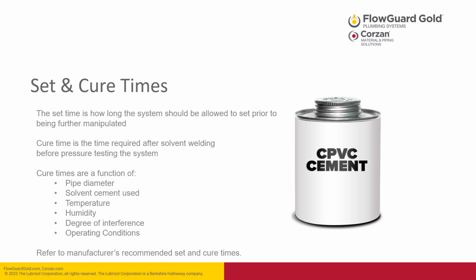Cure times are a function of a variety of factors, including pipe diameter, the type of solvent cement used, temperature, humidity, the degree of interference in the interference fit, and the operating conditions. Each manufacturer of solvent cement publishes a list of recommended set and cure times. Refer to their listings and manufacturer's recommendations for those set and cure times specific to the cement and application that you're using.